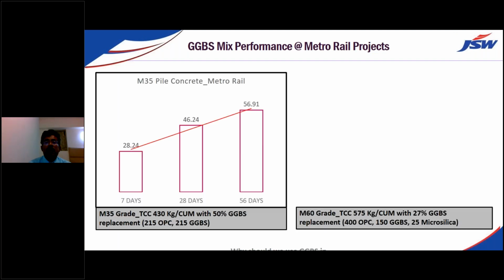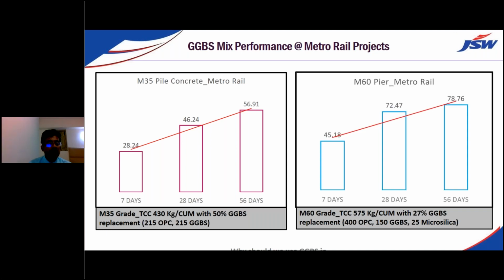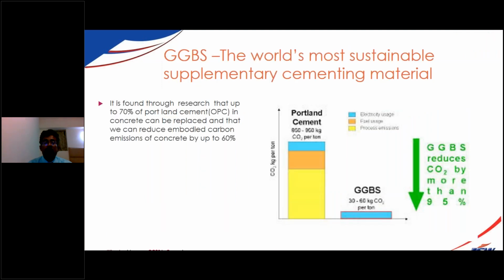Similarly, looking at the mix proportions at metro projects where we have done various mixes, M35 grade with 50% replacement, you see a gradual jump in strength, almost 10 MPa more at 56 days compared to 28 days in the pile mix. Similarly, M60 grade concrete has given better performance.